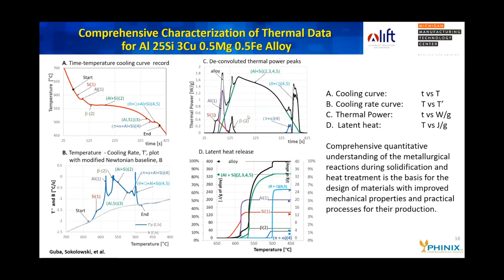So here is the thermal data that corresponds to this microstructure, and graph A shows the cooling curve, and you can see on the cooling curve you can correlate it with the formation of the particular phases in that cooling sequence that I just talked about. Cooling curve is difficult to read. If you differentiate it and look at the cooling rate and draw in the baseline, you can see the thermal peak associated with phase formation much more clearly.